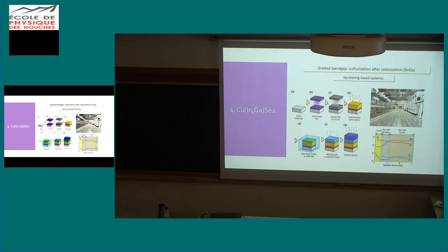And this is the other process used for grading in CIGS, using sulfur. So basically, gallium is kept at the back contact for band gap grading, but then you introduce a step where you sulfurize your surface. Then you increase the band gap of your surface with sulfur instead of gallium. This is the methodology used by Solar Frontier, the main company in the world producing CIGS, and it also works extremely well. Here you can see the gallium increase at the back and the sulfur increase at the front